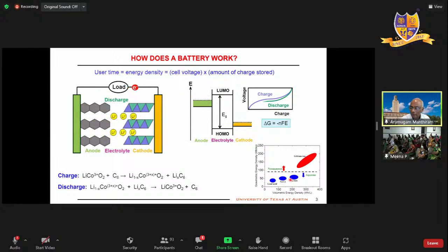So why are we replacing them with lithium-ion batteries? The reason is all these three batteries, lead acid, nickel cadmium, and nickel metal hydride, they all use water-based electrolyte. Lead acid battery uses sulfuric acid, that has water. Nickel cadmium and nickel metal hydride use potassium hydroxide, that has water. When you have water in the electrolyte, the band gap I was talking about is narrow. You cannot have more than 2 volt. So voltage is just less than 2 volt.